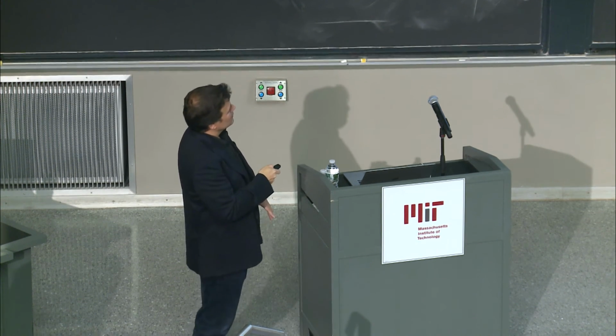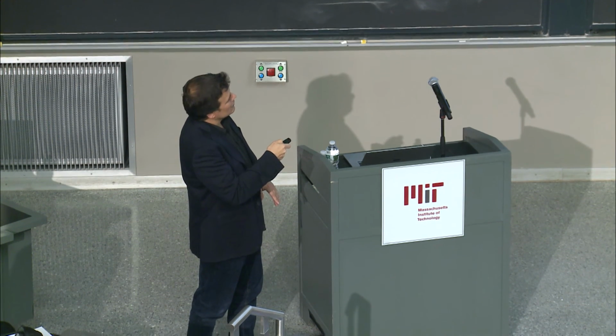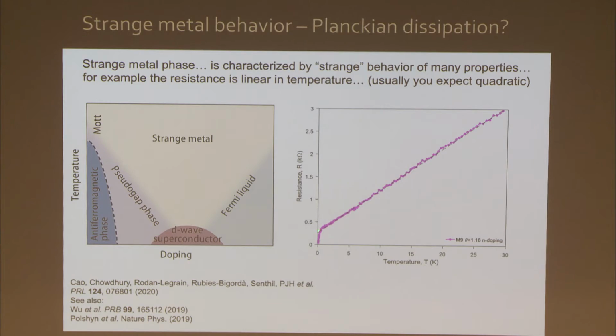And then, this is a different device where you can see that the resistivity is linear, linear, linear, until it just becomes superconducting right at 0.5 Kelvin. In fact, this behavior has now been extended down to 40 millikelvin. Magic angle graphene is the second strangest metal, strangest meaning going linear in temperature until the lowest temperature. There's only another system, a heavy fermion, which has been measured down to even lower temperatures. So this is something that plenty of people are interested in.